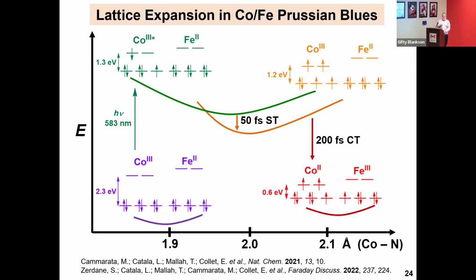And then the slow step is electron transfer from the iron to the cobalt, that is vibrationally gated, meaning that it goes through a vibrational state. And that's what we saw in the optically induced and thermally induced changes. That's the slow step in the reaction. That's the slow step in the electron transfer. That is what allows us to do anything in this project, because we do slow spectroscopy fast.